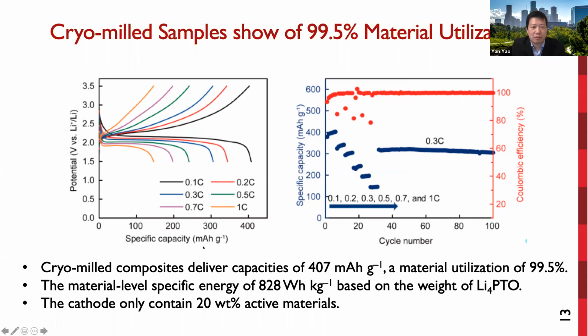Now the cryo sample reached a capacity of over 400 milliamp hour per gram, which is a material utilization of over 99.5%. So this is the first time an organic electrode material accomplished full utilization in a ceramic electrolyte-based battery. So the material level specific energy also reached 828 watt-hour per kg. This is only the material level, not the full cell level.